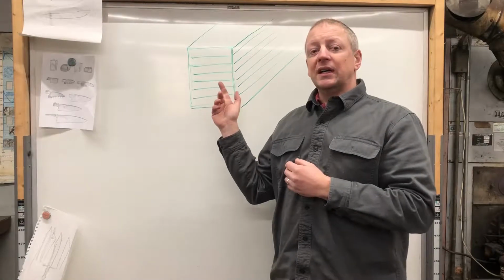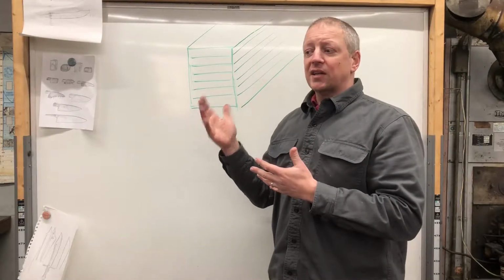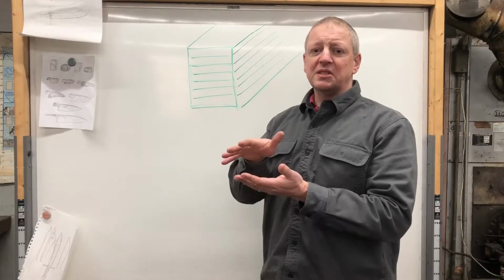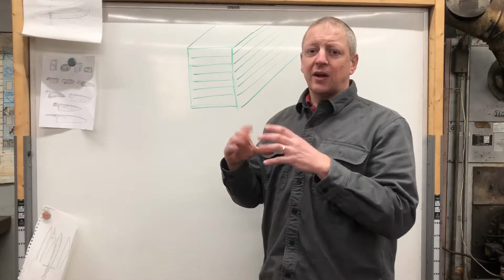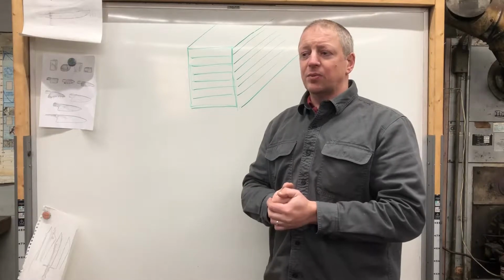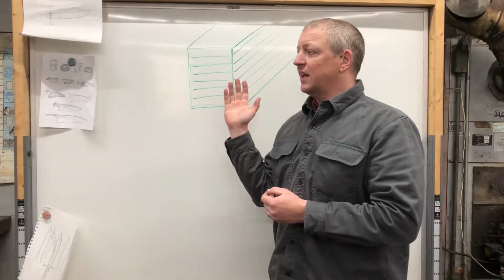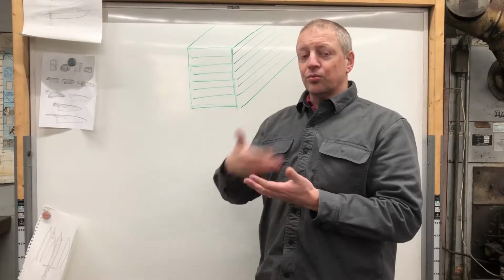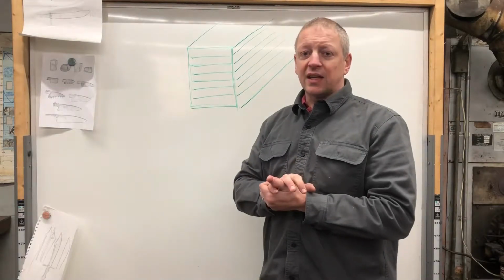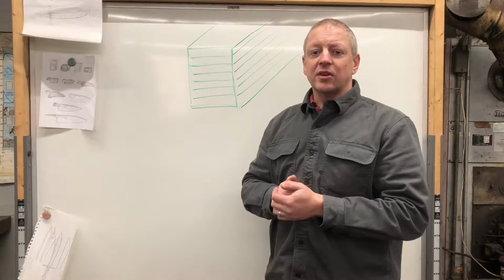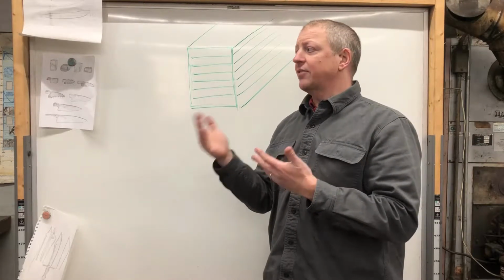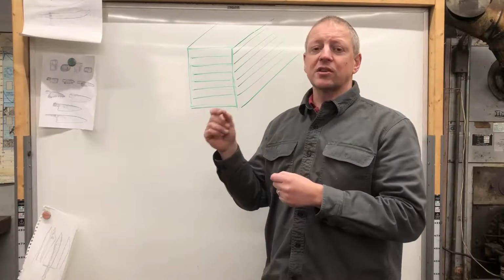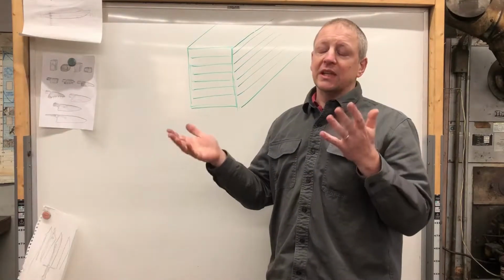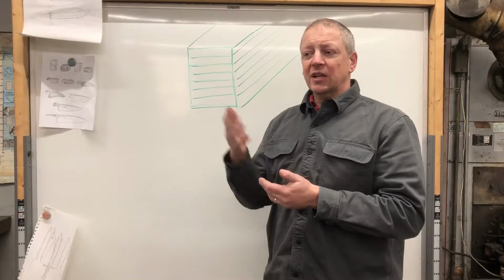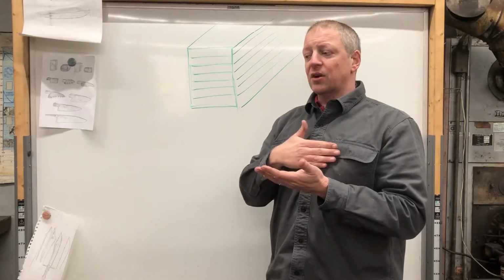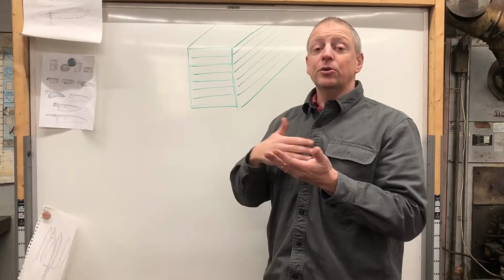So therefore, when we're doing a Damascus stack, we just take those mill pieces, throw them together in a stack, have it pretty tight, and we don't worry about cleaning it. When we are re-welding, when we're restacking, we always grind those surfaces fairly clean. You don't have to take off every single tiny little dark spot. You certainly can, but you don't have to. What you want to make sure you get rid of is all of that loose material.